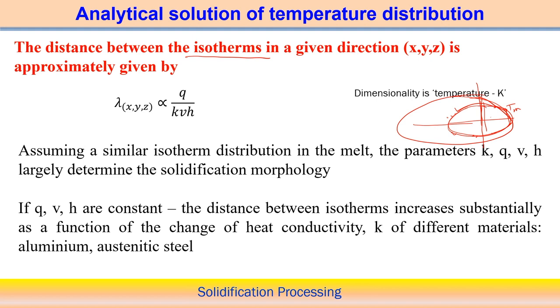conduction equation, and it is approximately for a particular direction spatial, the distance between the two isotherms. For example, this distance between the two isotherms is approximately given by lambda xyz. Xyz is a spatial distribution. We are not presenting this value in terms of time, rather in the spatial distribution of temperature. So the gap between these two is proportional to the heat applied to this welding plate, the heat conductivity, the velocity of the welding, and the thickness of the plate. All this matters to find out the different isotherms during this calculation.